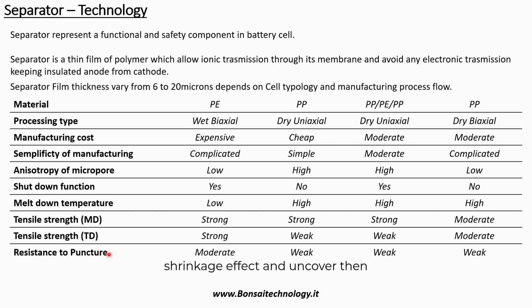Maybe you create some shrinkage effect and uncover the anode to the cathode, and this way the anode can touch the cathode and make some short circuit. But for sure, if the meltdown temperature of the separator is very, very small compared to the thermal runaway temperature, you cannot use the entire working temperature range of the battery cell, because you are limited by the melting down temperature of the separator itself.